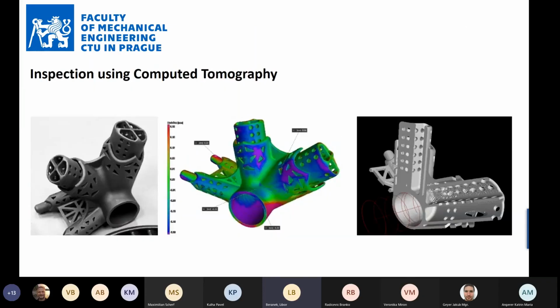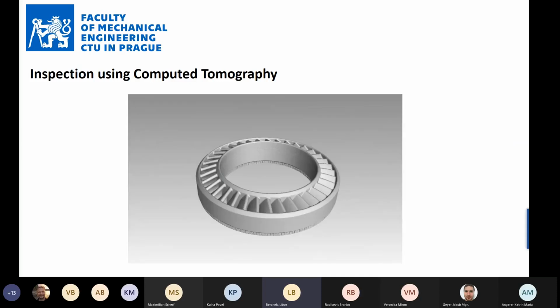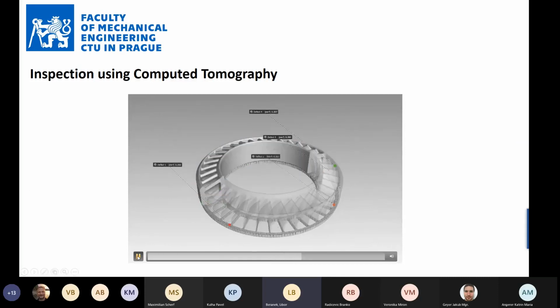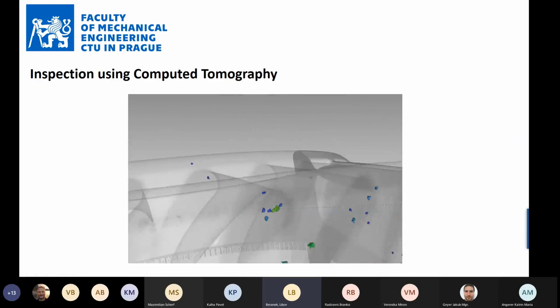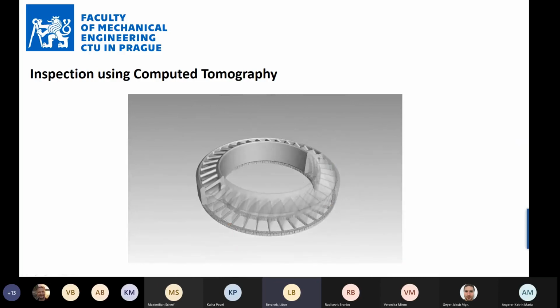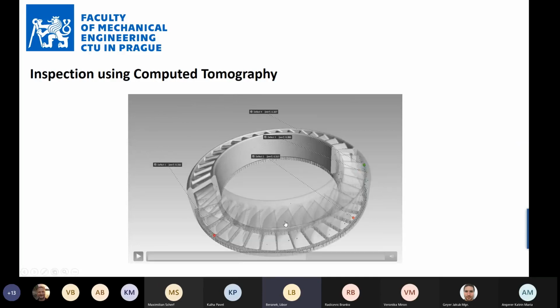Regarding the inspection, as I was mentioning, CT is a very productive technology which can help you gather information about the outer shape, and also helps you inspect the inside of the part without destroying it. So it is a typical technology for non-destructive testing. Also to mention that all the printed parts have some kind of porosity. Usually we are under 0.1% porosity. But when the printing parameters are not set properly, you can be not at the level of 0.1%, but at the level of single percent or sometimes even higher.